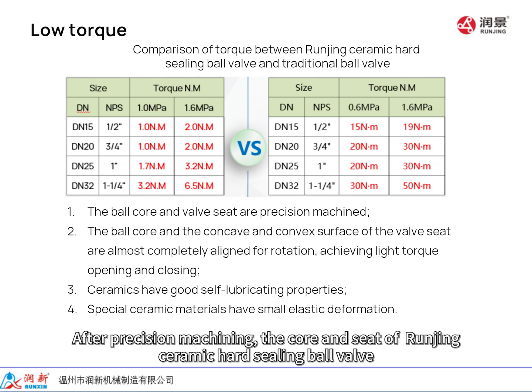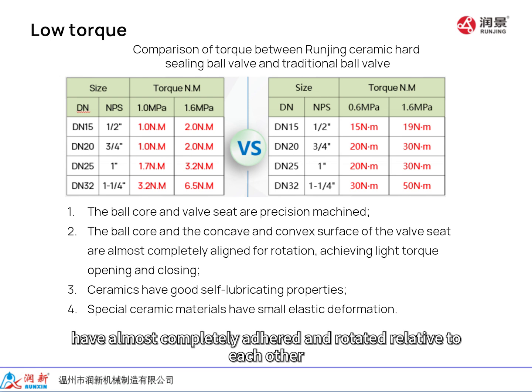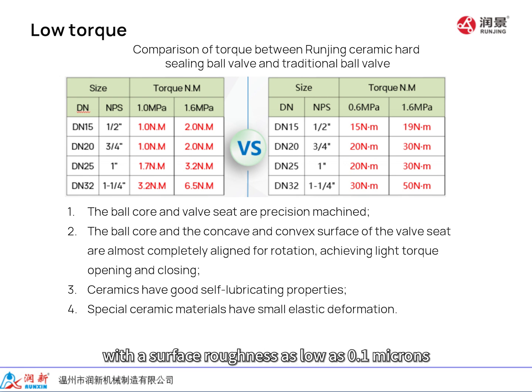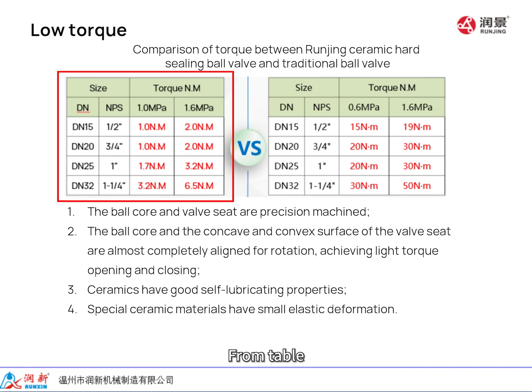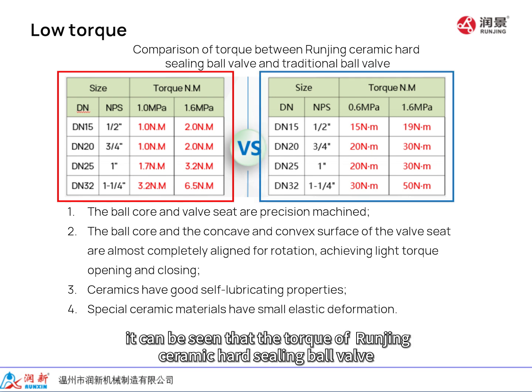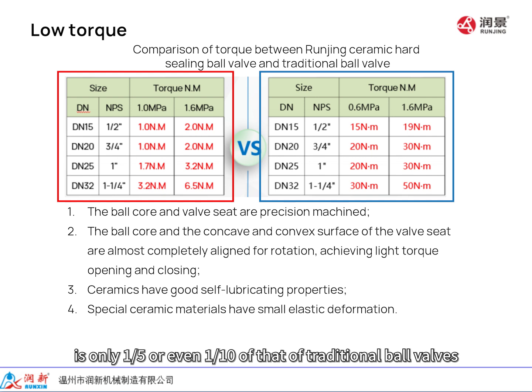After precision machining, the core and seat of Runjing ceramic hard sealing ball valve have almost completely adhered and rotated relative to each other, with a surface roughness as low as 0.1 microns. The material has small elastic deformation and good self-lubricating properties. From the table, it can be seen that the torque of Runjing ceramic hard sealing ball valve is only 1/5 or even 1/10 of that of traditional ball valves.